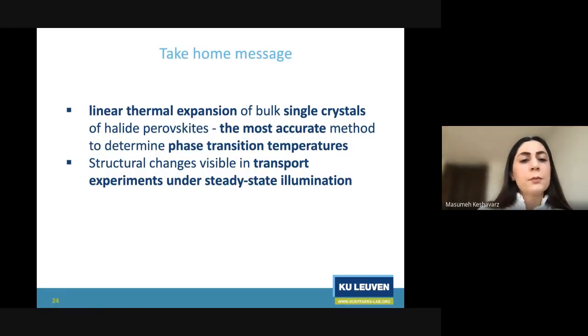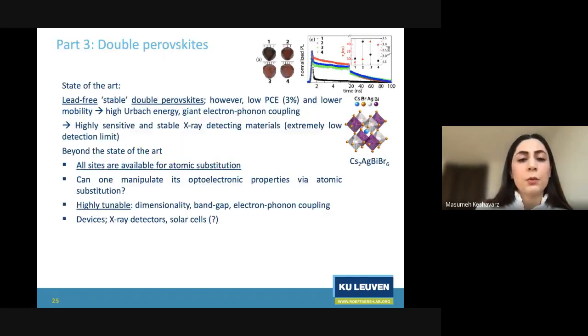Now let's conclude for this part that the linear thermal expansion of bulk single crystals of halide perovskites has been done, and this thermal expansion is one of the most accurate methods to determine phase transition temperatures. However, we need a complementary method to identify the exact phases of the crystals, the structure of the crystal. And structural changes are visible in transport experiments under steady-state illumination as well. And we compared the optoelectronic properties together, and we see the structural changes are actually changing the optoelectronic properties.